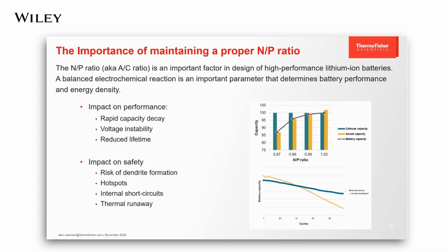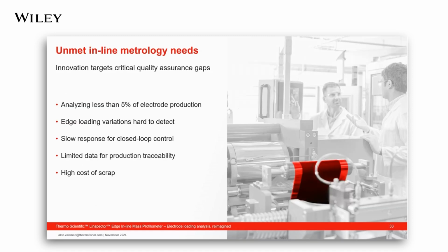An incorrect N to P ratio can speed up capacity decay and reduce the lifetime of the cell. It can promote the formation of dendrites, hotspots, and in extreme cases lead to thermal runaway. Close monitoring and tight control over the active material loading uniformity is of increasing importance. But until recently, the tools available to process engineers and quality teams for measuring electrode loading were limited to single-point or scanning sensors. As battery technology continues to develop, so does the need for more advanced metrology tools.